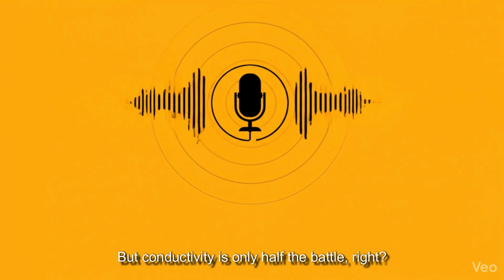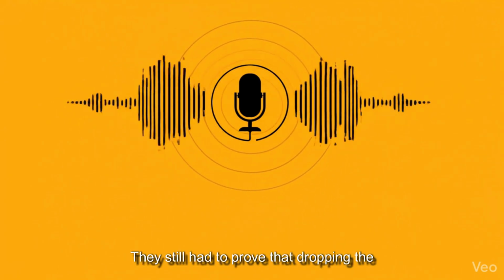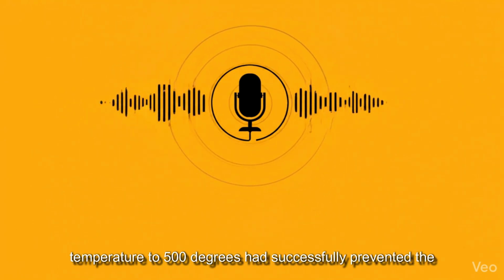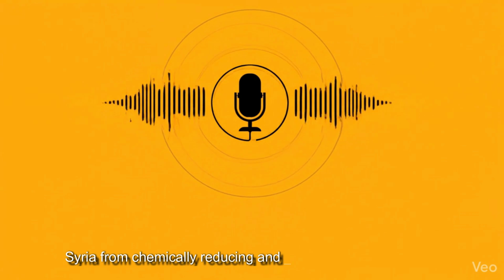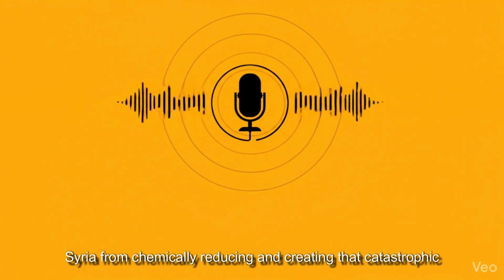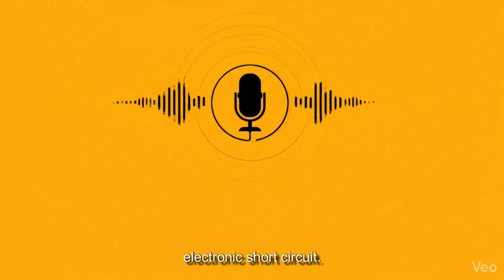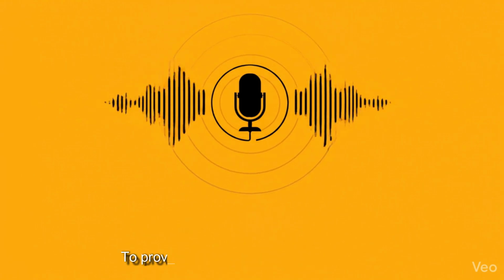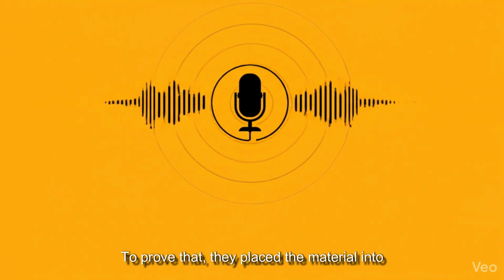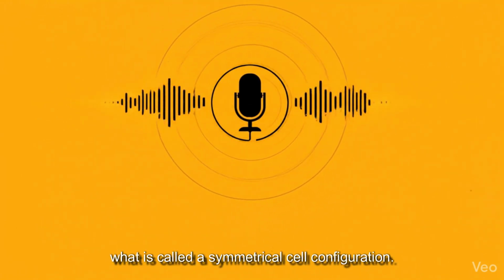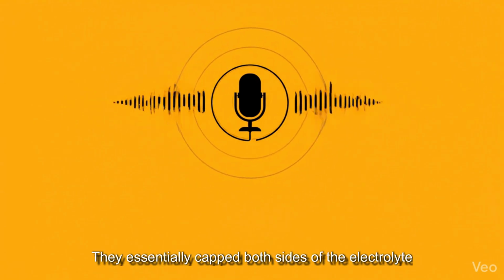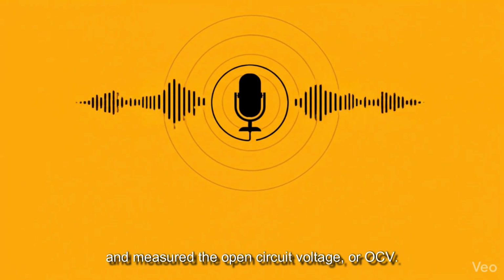It's a huge milestone. But conductivity is only half the battle, right? They still had to prove that dropping the temperature to 500 degrees had successfully prevented the ceria from chemically reducing and creating that catastrophic electronic short circuit. Right, the short circuit problem. To prove that, they placed the material into what is called a symmetrical cell configuration. They essentially capped both sides of the electrolyte and measured the open circuit voltage, or OCV.